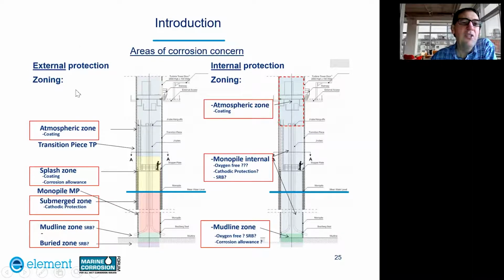If we look at the external surfaces, in the atmospheric zone above the seawater, we'd need to apply coatings to protect the transition piece. Then in the splash zone region, just above the water zone, we'd need to apply coatings again and have some additional corrosion allowance because of the severity of the environment. Then if we move down the monopile below the waterline in the submerged zone, we'd need to apply cathodic protection and coatings as well. And then in the mudline zone and the buried zone, there is a risk in these regions of sulfate reducing bacteria activity, depending on the particular environment.